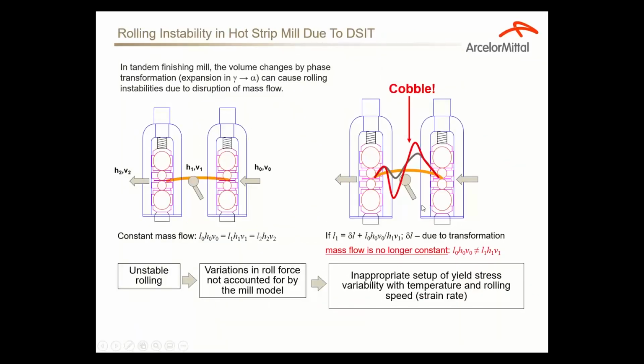Why is it important? The transformation of austenite to ferrite changes the volume of steel, and so it changes the mass flow. So when the steel is transforming in the mill, the mass flow is no longer constant. If the mill knows this, it can be taken care of. But if the mill does not know this, the temperatures are not properly set up, the strip will cobble in between the stands because mass flow is not constant. So this is very important information that we supply to the mill to make sure that the rolling is stable, to set up the interstand tension for the hot strip mill, and avoid cobbles, because cobbles are very costly to fix.